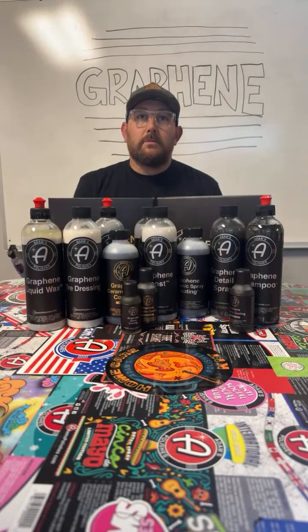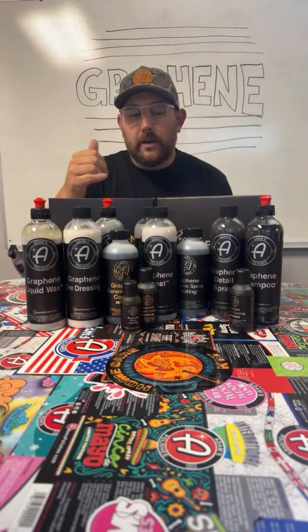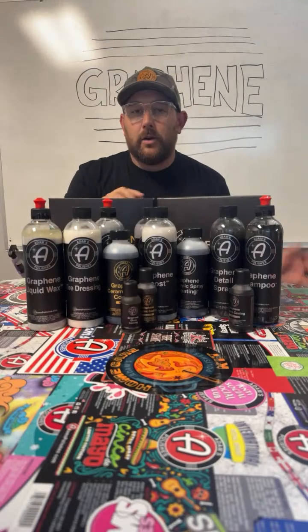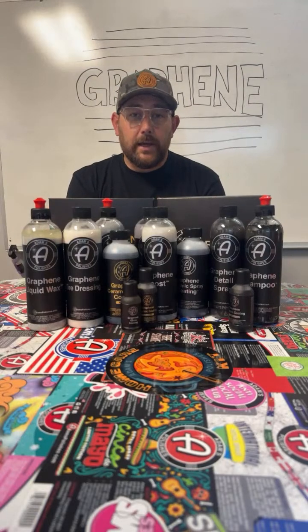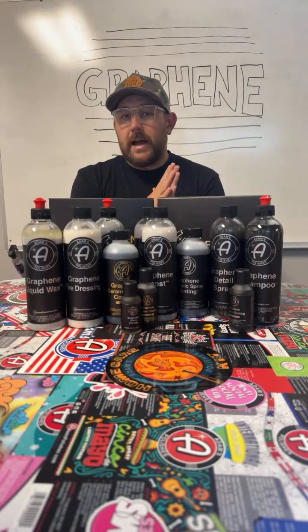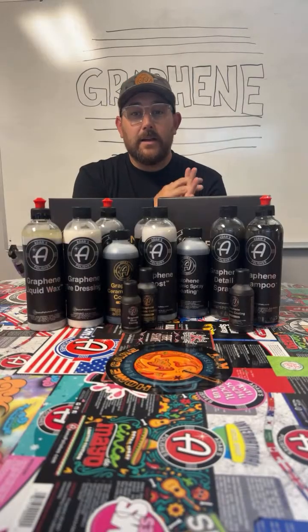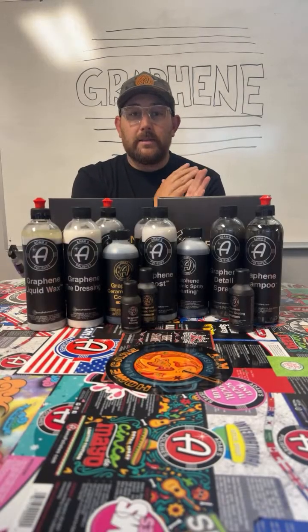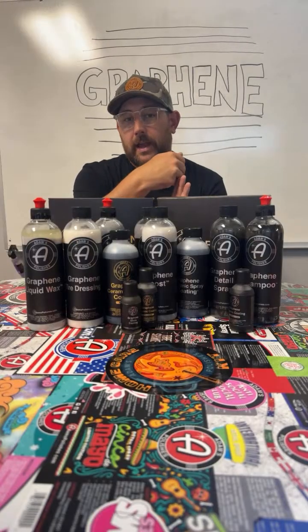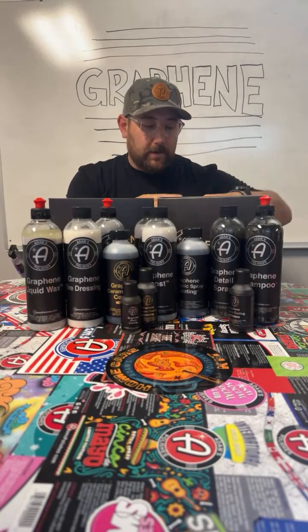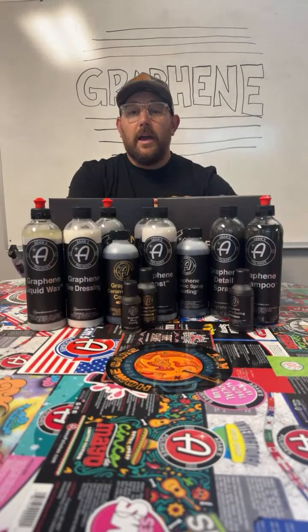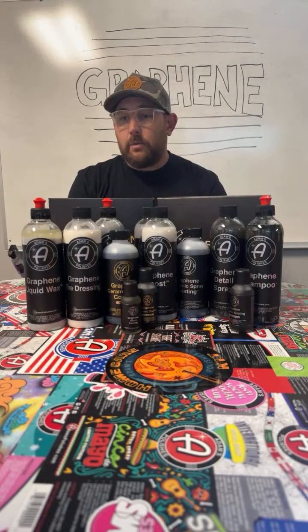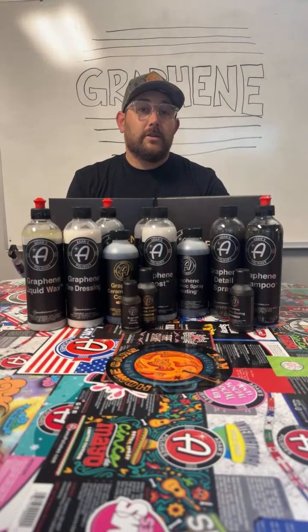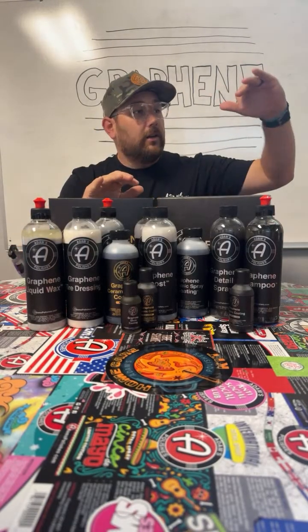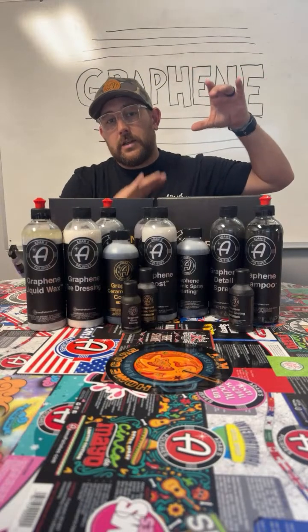The reason why we did it like that, and this is something we found out later, was that when you put a graphene ceramic coating on the windshield, which we advertised from the beginning, we started learning that the graphene ceramic coating wasn't actually penetrating into the pores of the glass. And so when people would use their wiper blades, because they're rubber and abrasive, and dust and dirt get trapped between your wiper blade and your windshield, it would abrade the graphene ceramic coating off within a couple months, real quick, to the point where you could see a color difference of where your wiper blade wasn't touching versus where it was.